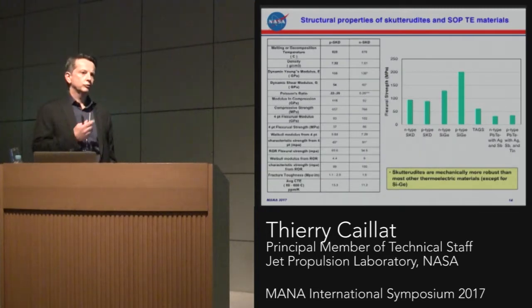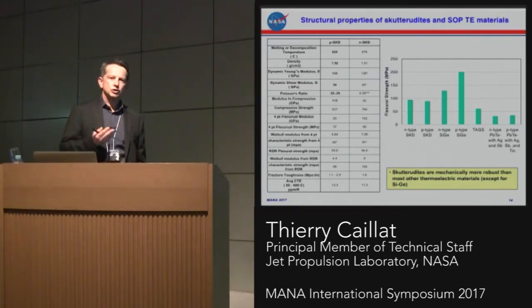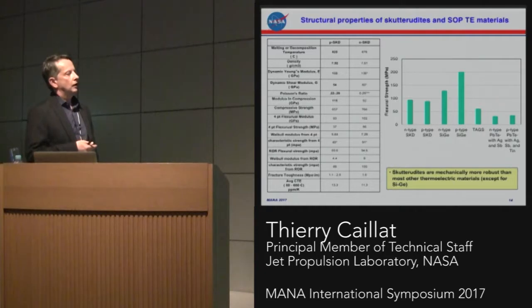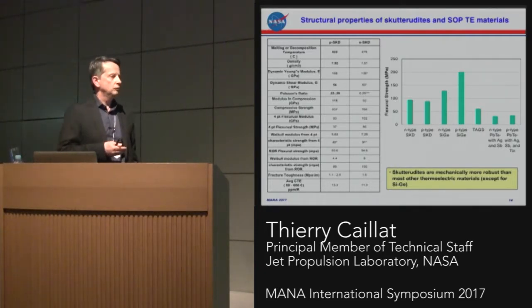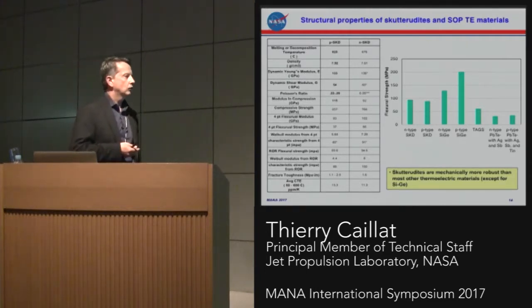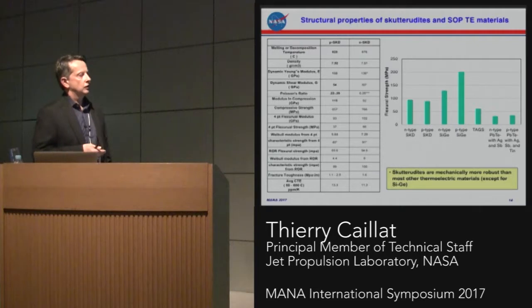One thing which is very important, I'm going to touch upon, is mechanical properties. Those things are not going to be seeing a lot of thermal cycles, but large delta T's are going to be applied across those materials. So they need to actually withstand some of the stress associated with potentially CTE mismatch and other type of things. So in general, the skutterudites are actually doing fairly well. They are actually brittle ceramics, so they do better in compression than in tension. So that's when you design your material and your couple, you need to make sure that eventually they're going to be in compression, not in tension. And essentially, the materials are actually doing better in terms of mechanical properties. The skutterudites are better than the lead telluride and the silicon germanium.